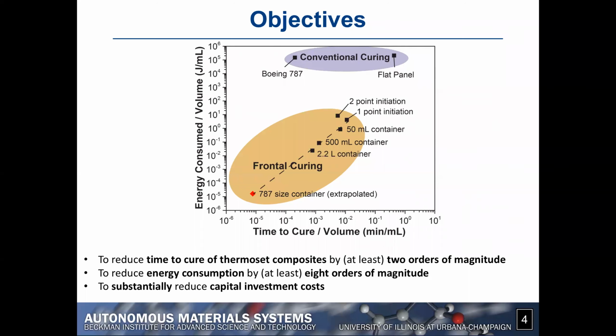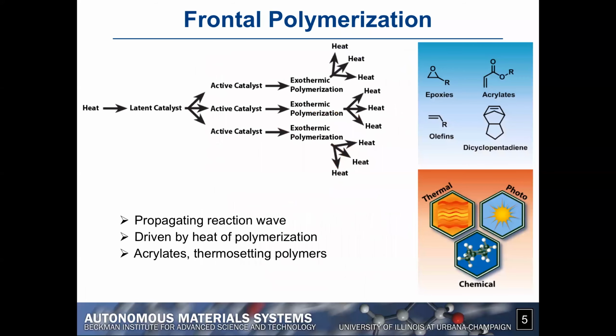But what we would like to achieve is to reduce the energy consumed by many orders of magnitude. We're talking about 6 to 8 orders of magnitude compared to conventional methods, and at the same time reduce the time for the curing process by about a factor of 100. And at the same time, we would like to achieve this cure outside of an autoclave. The basic method that we propose is frontal polymerization, which is schematically represented here.